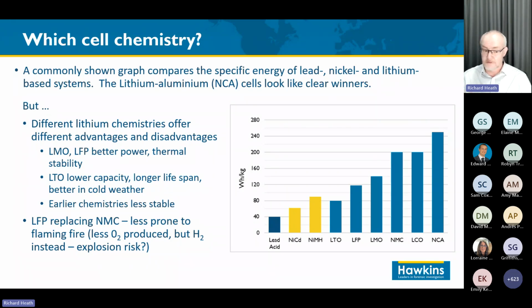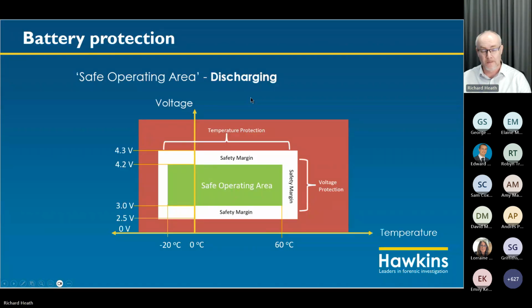And some of those early chemistries were not as stable as the ones we are currently using. And in particular, the LFP batteries that are now replacing the nickel manganese cobalt are less prone to a flaming fire because the chemistry means they produce less oxygen if they do go into thermal runaway. But the downside is they produce hydrogen instead. So you skip the fire and have an explosion risk as an alternative.